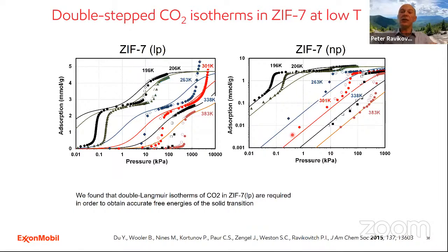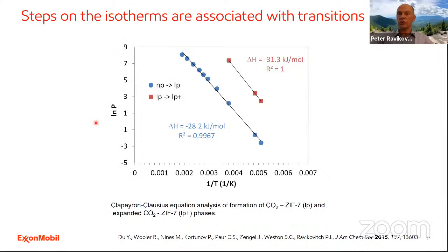So what you can try is to fit these isotherms, which we did here with double Langmuir isotherms, and these fits help you to understand what's going on, because you can see there is a nice Langmuir fit of the isotherms at low pressures, which corresponds to the narrow pore phase. And then there is a decent fit of double Langmuir isotherms at higher pressures. And what you can also do is plot the pressures of this transition as a function of temperature using the Clapeyron equation. And you can see for the first step, all these points line up on the Clapeyron equation.